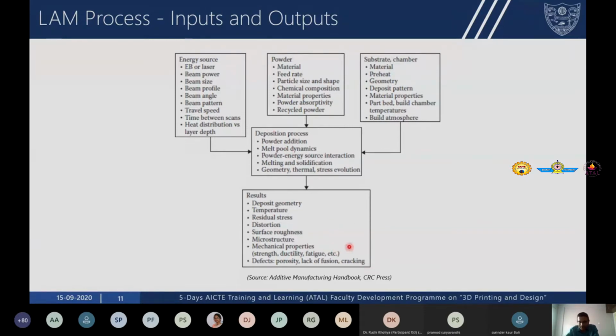So all this occurs in the deposition process, and the results that you need to look into are the deposit geometry, the build conditions, temperature, both the distribution as well as the maximum temperature, residual stress, distortion, and the surface roughness. As I showed you earlier, the surface roughness of the deposited components is very high. Then the microstructure, and the properties such as the strength properties, the fatigue properties, and so on. And finally, the defects: lack of fusion defects, porosity, cracking, and so on. Okay, so you have inputs coming from a number of sources, then you have a large number of deposit characteristics that you need to understand. All these really increase the complexity of metal additive manufacturing, or as I'm calling it, laser additive manufacturing, because we are discussing that the laser is the heat source in the metal additive manufacturing process.